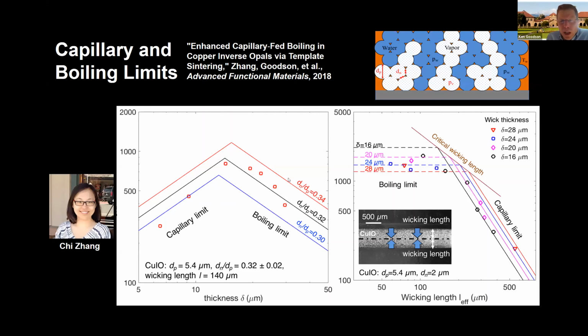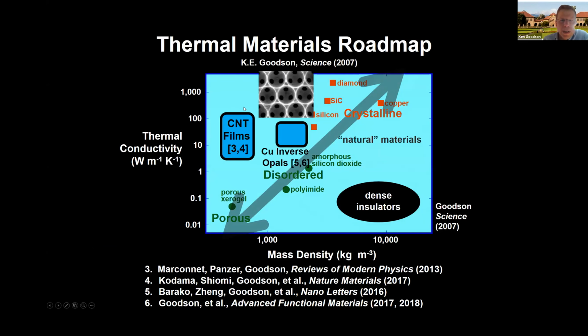And there's also relevance of the necks versus the pore size, which she investigated. There's also the wicking length and the impact on the boiling limit. And if you get to the critical wicking length, you're basically balancing the needs for boiling physics with the capillary length of the structure. And one opportunity is that if you make these porous media, you have an opportunity to really improve the balance between capillary and boiling limits.